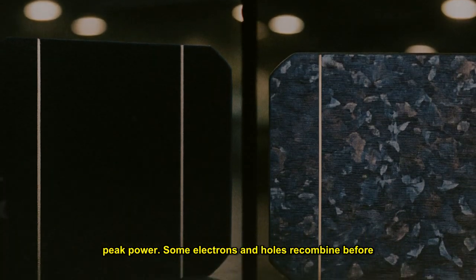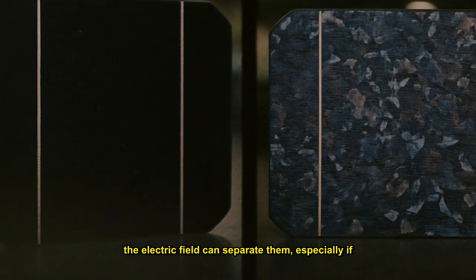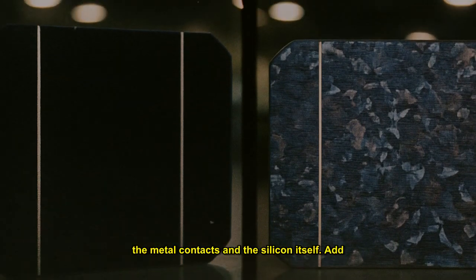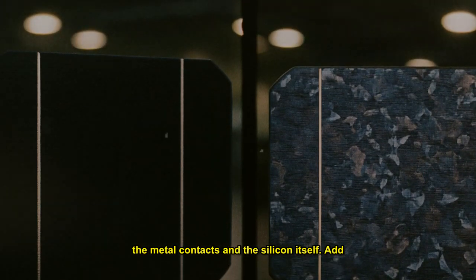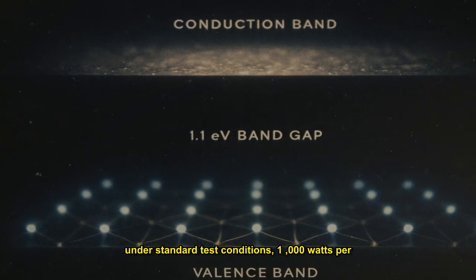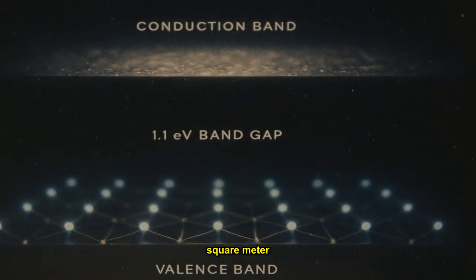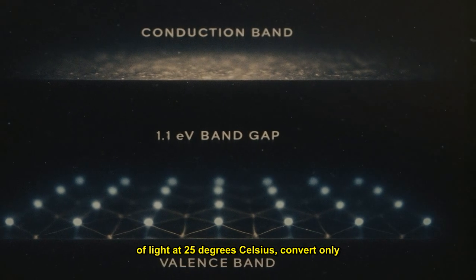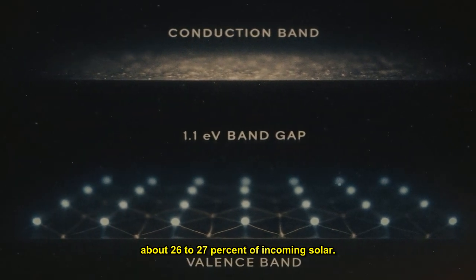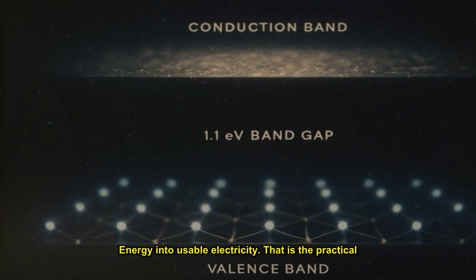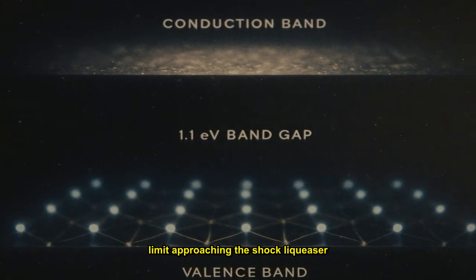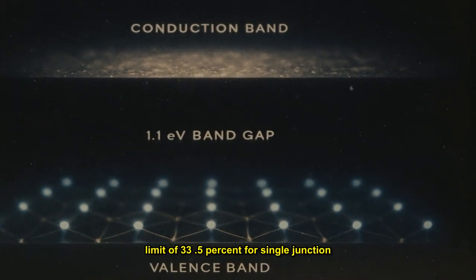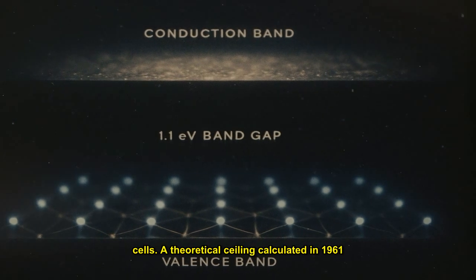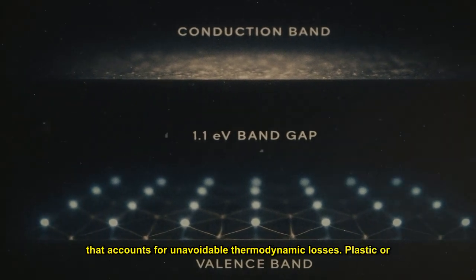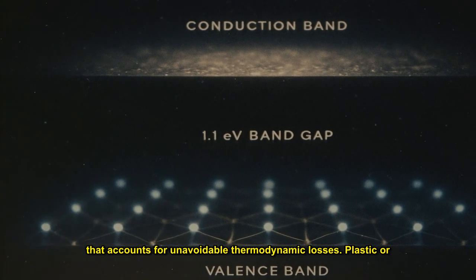Some electrons and holes recombine before the electric field can separate them, especially if there are crystal defects or impurities. Some current gets lost in the resistance of the metal contacts and the silicon itself. Add it all up, and even the best silicon cells under standard test conditions, 1,000 watts per square meter of light at 25 degrees Celsius, convert only about 26 to 27% of incoming solar energy into usable electricity. That is the practical limit approaching the Shockley-Queisser limit of 33.5% for single-junction cells, a theoretical ceiling calculated in 1961 that accounts for unavoidable thermodynamic losses.